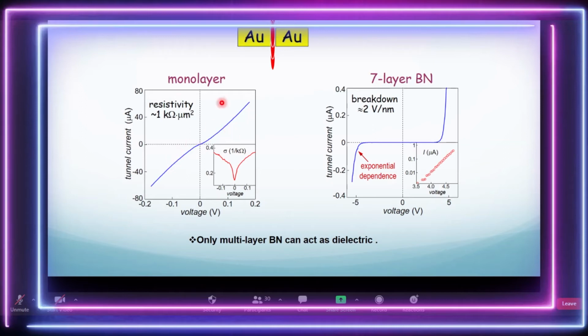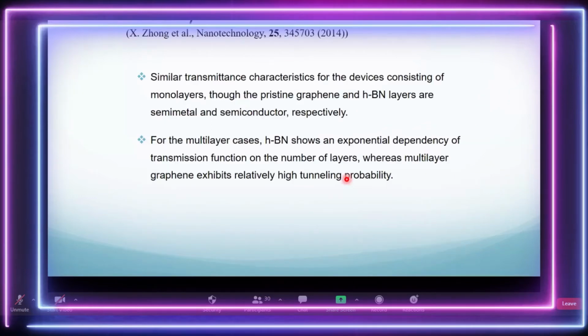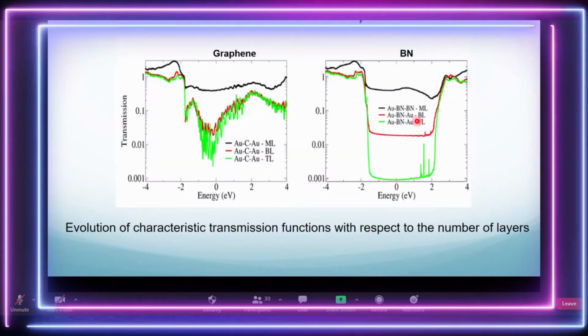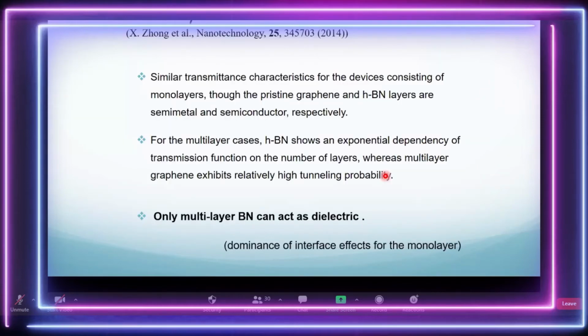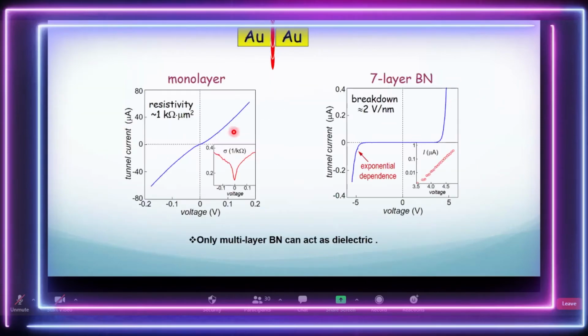But when he goes to a thicker sample, from monolayer to 7-layer, you can see, wow, it's just like a diode, a semiconducting material. So you can see the interplay, which we found earlier also, that the thicker the boron nitride sample, the more it mimics the material's property. And it really comes out nicely in experiments. So it really feels good that at least something is nicely going on between our work and what I call the real world.